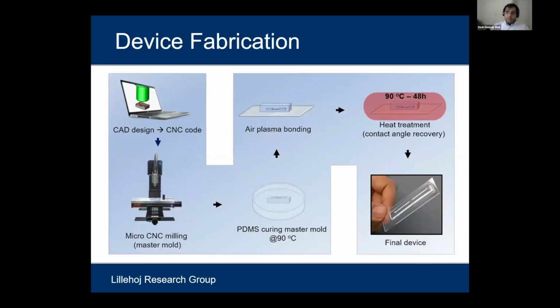So the fabrication of this device was done in our lab. What we did is we designed this. We had the design in a CAD software. We created a CNC code. We generated the master mold using a micro CNC, and then we cured PDMS on top of it, and then did the air plasma bonding. And then there was a step which we added to the whole process, which is heat treatment for contact angle recovery, which I will try to explain later on slides. And after the bonding, when we do the plasma bonding, we have the device.